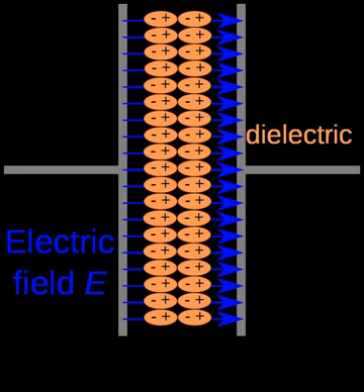Other potential materials include microwave dielectrics and carbon nanotube composites. In 2013, multi-sheet layers of strontium titanate interleaved with single layers of strontium oxide produced a dielectric capable of operating at up to 125 GHz. The material was created via molecular beam epitaxy. The two have mismatched crystal spacing that produces strain within the strontium titanate layer that makes it less stable and tunable. Systems such as barium strontium titanate have a paraelectric-ferroelectric transition just below ambient temperature, providing high tunability. Such films suffer significant losses arising from defects.